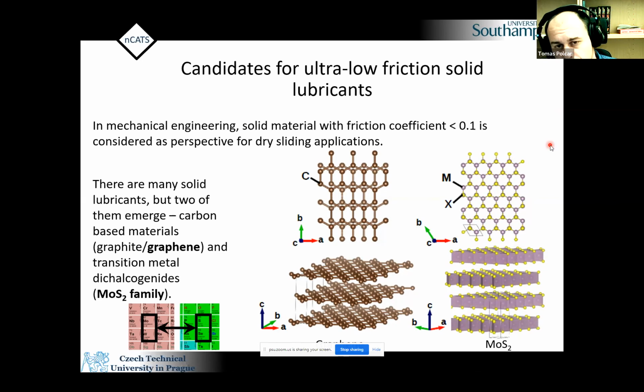The idea of what to do with these coatings, with these materials, was not that clear for many years, because we can produce them as a bulk, as a crystalline material, but they really struggle. If you use just graphite, you will realize that it is an excellent material for humid air, but it's not really working very well in vacuum. And molybdenum disulfide, for example, is the opposite case. It works very well as a crystal, it works very well in vacuum, but in air it is very easily damaged and oxidized and so on. So we need to look for a better solution, basically, and how to use them.